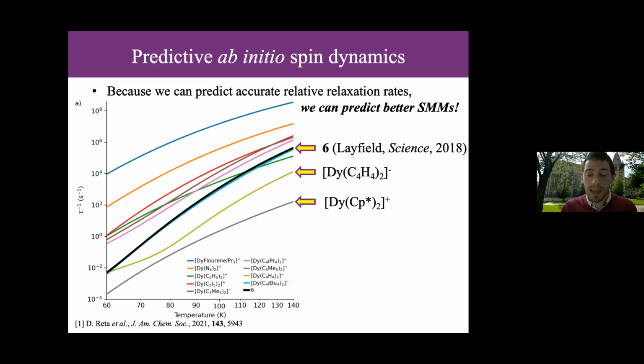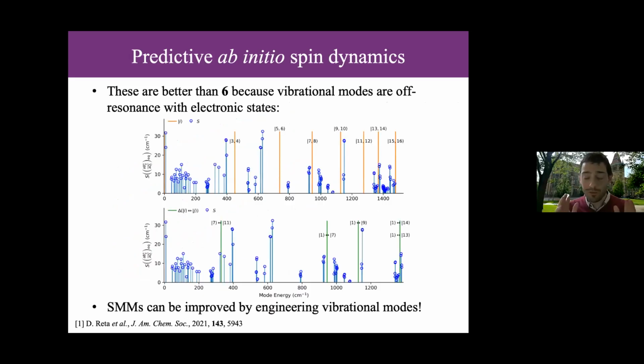In actual fact, this doesn't have a crystal field splitting that's any bigger than Layfield's molecule, and neither does this one. Actually, they're both very similar. So it isn't actually the crystal field splitting for these latter two which gives you the different properties. It turns out to be vibrational modes. And so they both turn out to be better than the Layfield molecule because all the vibrational modes happen to be off resonance with the electronic states. Now, that's something that's very hard to predict. You certainly can't just write a molecule down on paper and say, oh, it's going to have that property, but you can calculate it.